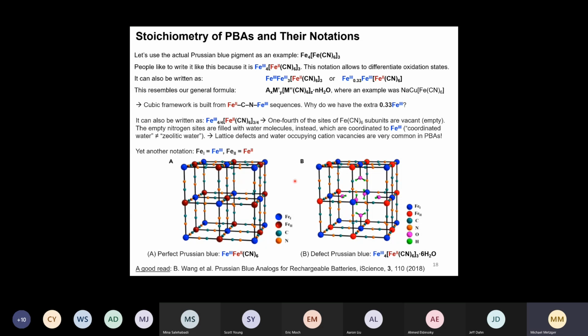I think in this case, if you think about it, you actually need this defect. That's also described in this paper. So this structure that they sketched up here on the left-hand side would actually not check out in terms of the oxidation states, because these cyano groups are typically -1, and then you have Fe2+ and Fe3+. So this is -6, but you end up with still a -1 overall oxidation state. So the way this is drawn here, it would not be neutral. You would actually have to have potassium or sodium intercalated here.